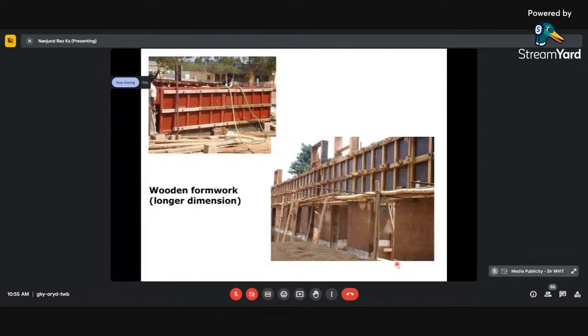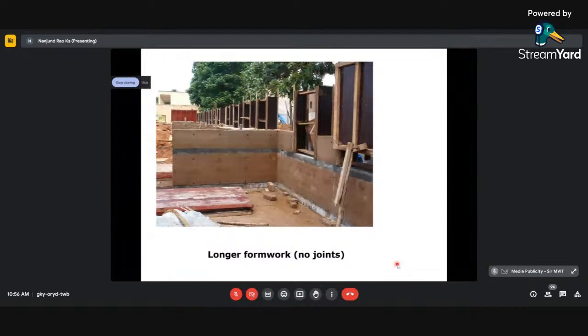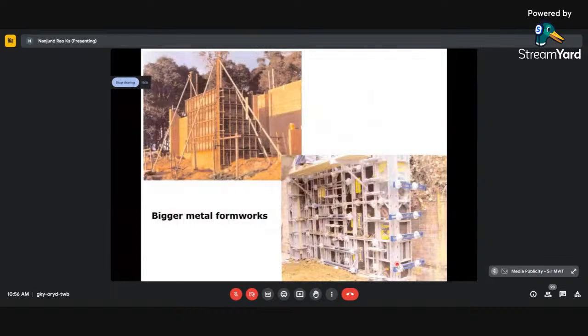Now, when you want to build large walls, then you also use large dimension formworks. But the problem is, when you have such long lengths, there could be shrinkage cracks. You can see this more so if it is in the unstabilized form. So you can see some long formworks without joints. People don't require joints, but later there will be cracks. Then again, you have to treat those cracks. Otherwise, insects, ants, everything can create trouble within, if it is a house or even any other building for that matter. So these are all bigger metal formworks. The formwork cost goes up, and you can afford such very big metal formworks only when you have a large housing complex, building 500, 600 houses.